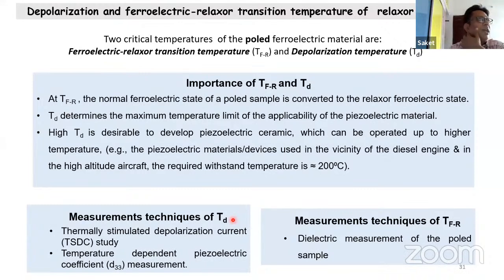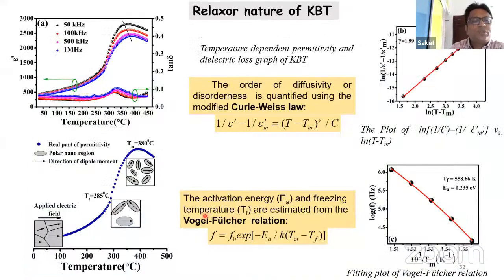So we put in a little effort and performed several experiments using the impedance analyzer or dielectric measurement for the poled and unpoled samples. Poled means you have to pole the sample, because whenever you are talking about piezoelectric properties, you have to electrically pole the sample. All the domain orientations should be in the same direction. So for that we pole it under a DC applied field for some time, so that the maximum number of domains are in the same direction. So we have successfully found it like this.